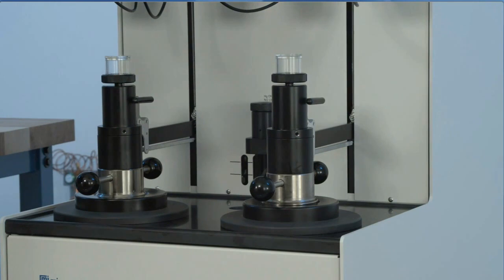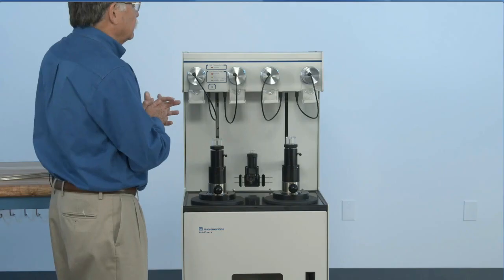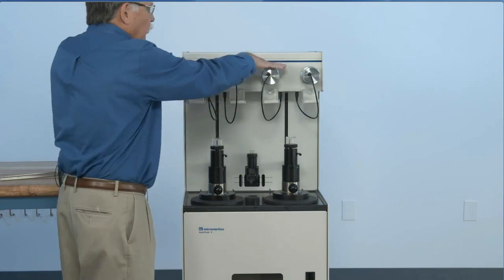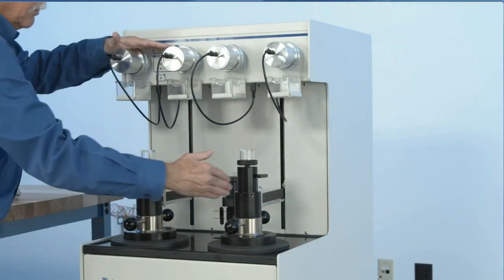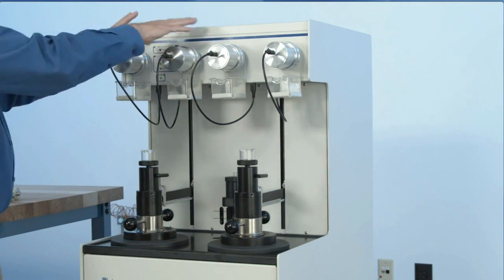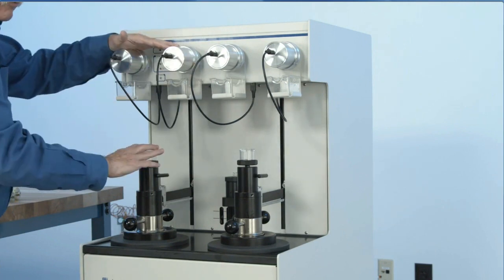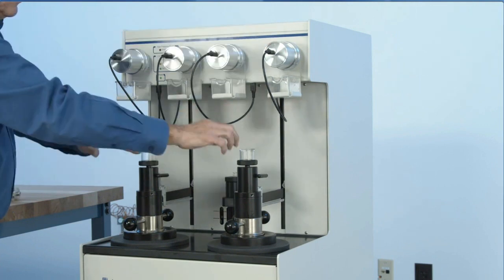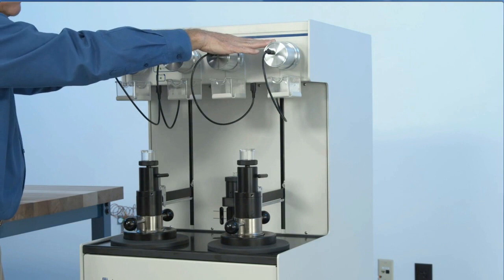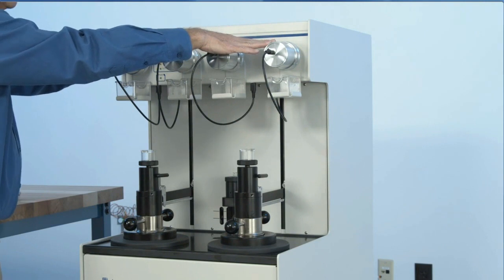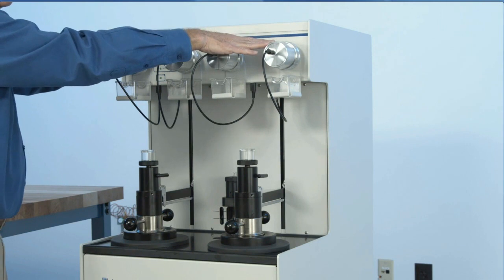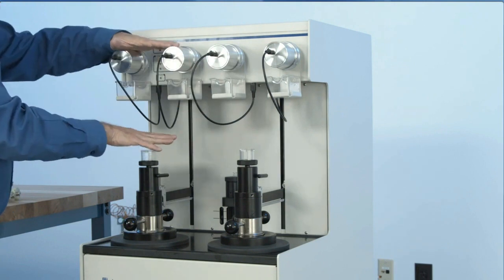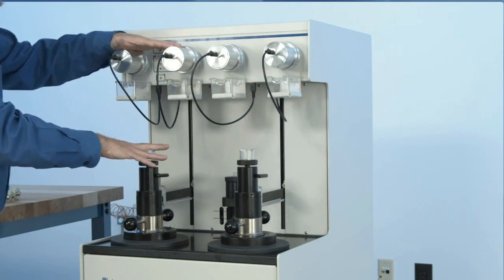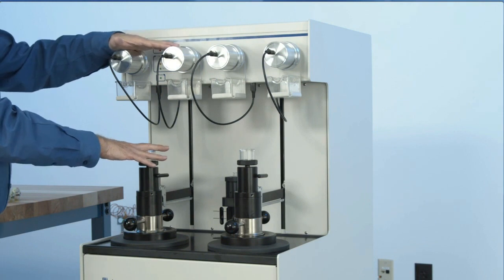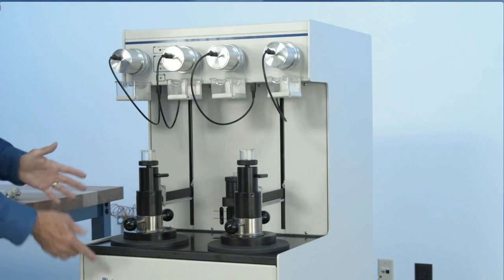Speaking of that, there are 4 instruments in the AutoPore 5 series. 2 of them have 4 low pressure ports, as we see here, and 2 high pressure ports, as we see here. The other 2 only have 2 low pressure ports and 1 high pressure port. Now, for the ones with 4 and 2, one of those goes to 33,000 pounds maximum pressure, or 227 megapascals, while the other one goes to the full 60,000 pounds per square inch, or 414 megapascals. The same for the unit that only has the 2 and 1 configuration, a 60,000 psi maximum or a 33,000 psi maximum.